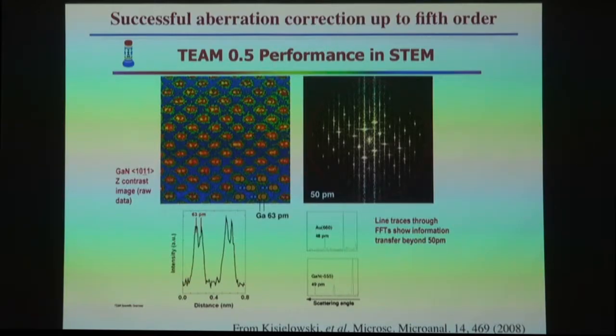And here is gallium nitride in the 10-11 projection. And in this projection, those yellow spots are the gallium atom columns separated by 63 picometers. And you can see that they're well resolved. Although you do still have a problem if you're looking at the image, you could ask yourself, where are the nitrogen atom columns? Structural model here, there are the gallium atom columns. The blue corresponds to the nitrogens. Nitrogens are not visible in this annular dark field image.